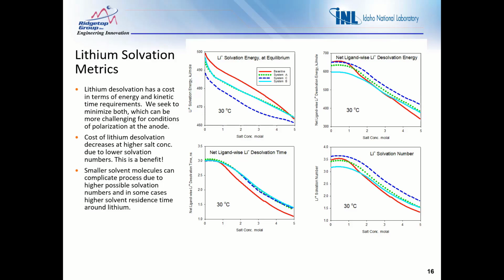So the panel right next to it is the net ligand-wise lithium desolvation energy plot. And that harkens back to the previous slide. As you start to pick off solvators one by one, the binding energy of the remaining solvents around the lithium gets a little bigger because their distance of approach, or their standoff distance between center of lithium ion to center of the polar moiety within the solvent, starts to decrease. So that increases the binding energy. That's why these values, net ligand-wise desolvation energy, are higher than what you saw in the left panel, because we're sequentially taking off these solvators.